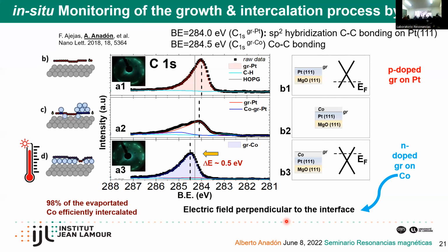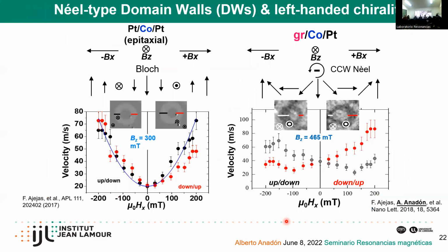So we thought that this could be one thing we could take advantage of to create, for example, chiral domain walls. So the origin of chiral domain walls sometimes comes from the DMI, the Dzyaloshinskii-Moriya interaction. And it's possible to measure this effect, these chiral domain walls, by studying how domains grow with pulses. So if we take, for example, a domain like a circle, we can apply pulses of magnetic field, going up or down, and we see that in a platinum cobalt platinum system, in which the DMI is 0, we have a symmetric system when we go from up to down or down to up in the magnetic field. But if we look at the graphene cobalt platinum system, we don't see the same effect. We have a different behavior going up and down or down and up. And this is related with the Dzyaloshinskii-Moriya interaction.